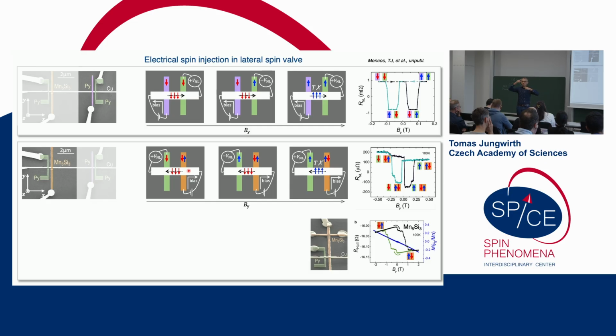But what happens is that as you push the spin polarized electrons into this channel, there is a non-equilibrium occupation of spin up and spin down states, and because you basically flip the chemical potential of the spin up and spin down electrons, there is a gradient of that, and so they will diffuse. So there's a diffusive spin transport in the opposite direction. And so the spins are diffusing, and then they create a non-equilibrium chemical potential on the other side, and you can measure it as a voltage on the other side. Okay?